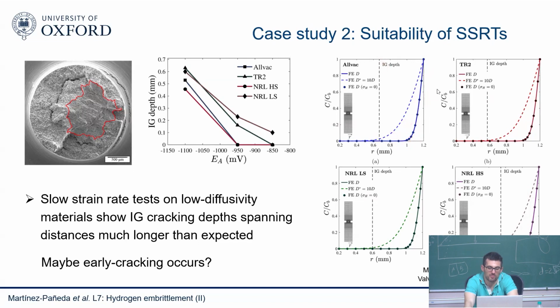And we even tried, because some people argue maybe hydrogen moves faster through grain boundaries or other things, so we tried increasing the diffusivity 10 times, which is kind of a very upper limit. We don't even see any of that in permeation, so probably it's much smaller than that. But we tried increasing 10 times, and this is the color dashed line. And you see, even increasing the diffusivity 10 times to account for uncertainties, we don't really get there. So something must be happening. There's a reason why hydrogen is stuck here, but embrittles a piece of material that is somewhere there. So the hypothesis is that maybe early cracking would occur.